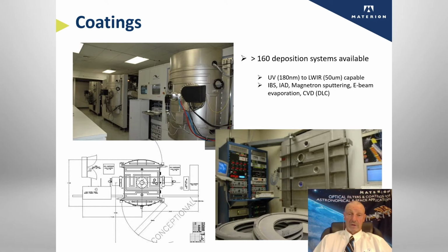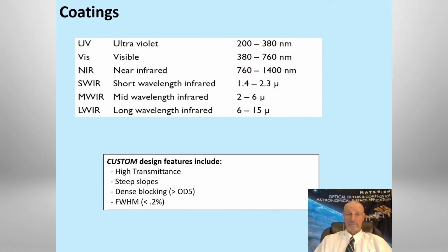So for the coatings, as I mentioned, we have over 160 systems available covering a wide range of processes from IBS to IAD to E-beam evaporation. For long-wave and mid-wave coatings, typically you're going to employ E-beam evaporation because that's the best fit to get the spectral performance that you're looking for. When we're talking about mid-wave and long-wave, we're talking between 2 and 15 microns. Each band that we make is custom designed to provide extremely high transmittance, steep slope, dense blocking, and we also can make narrow bandwidths as narrow as 0.2% in this wavelength range.